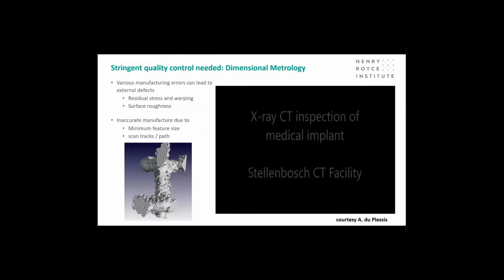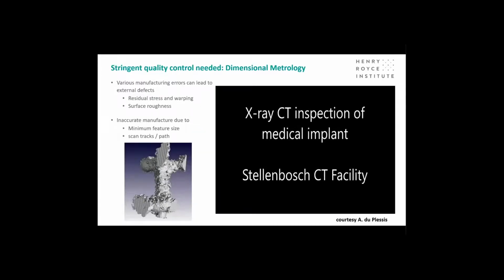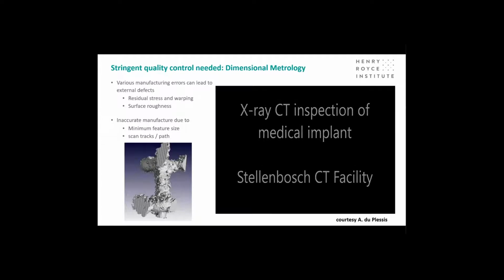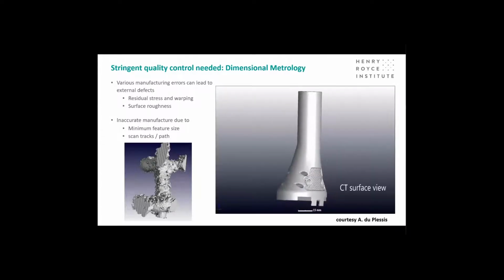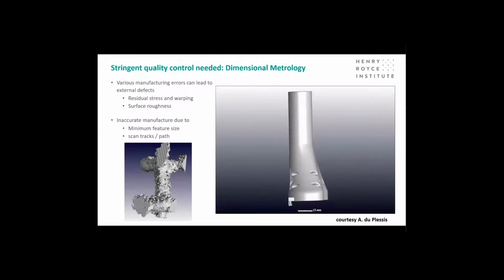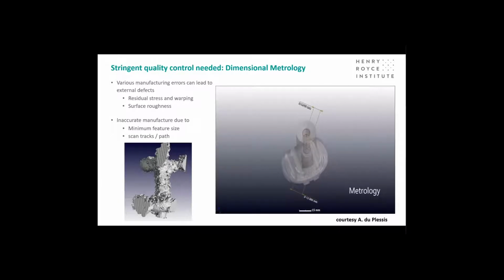slower time scale X-ray CT done either in the lab or at the synchrotron. And I want to give a little bit of an insight into some of the things that you can do using lab CT. Of course, the first thing is that you can qualify and quantify the accuracy of your part. And here is a little video from Anton du Plessis in South Africa, which shows that part I showed at the beginning. And using CT, you can accurately measure the internal diameters, you can measure the external diameters, and of course you can measure the lattice work.